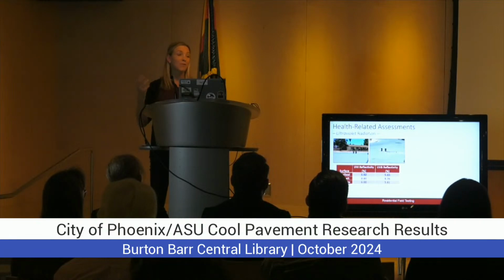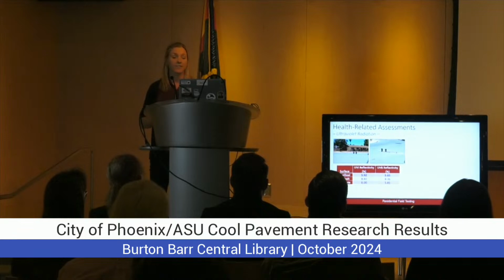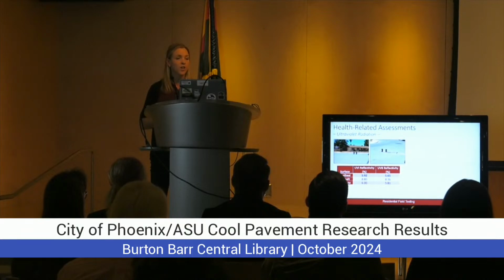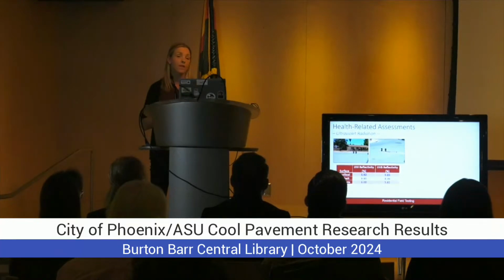This is a question we get asked about a lot. Is it higher UV radiation over the surface? So in 2022, we decided to test that. I have these UV index and UVB sensors, and on average, the cool seal percent reflectivity from the surface was lower than asphalt and concrete, just by taking the incoming and outgoing and dividing it.